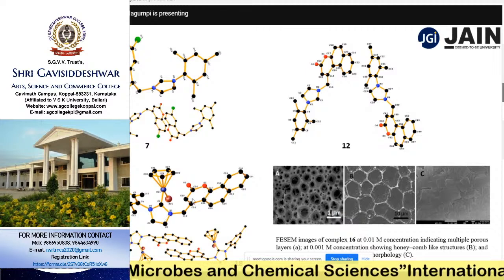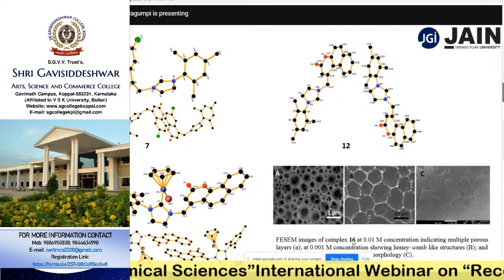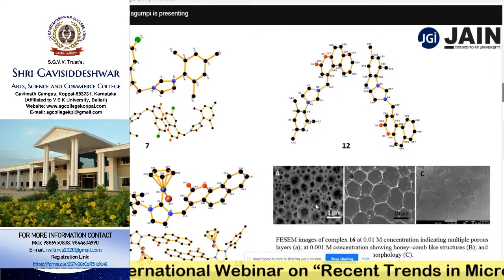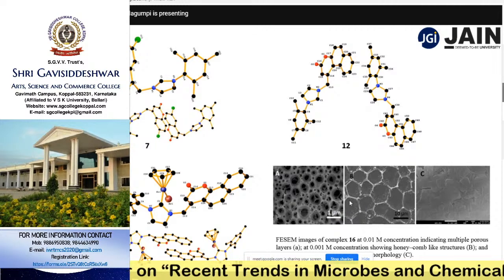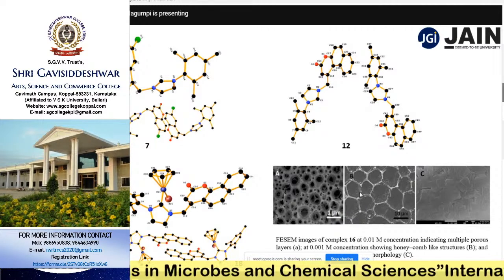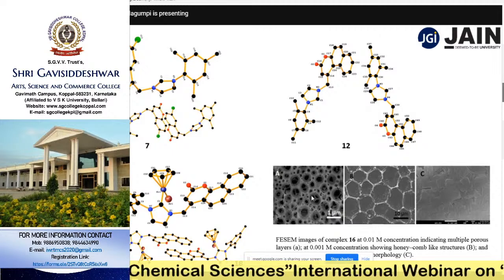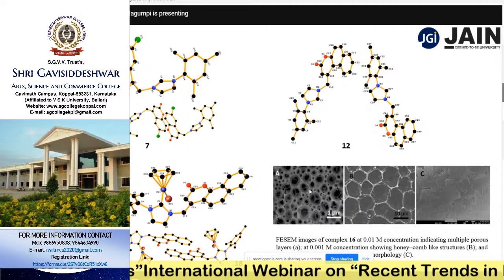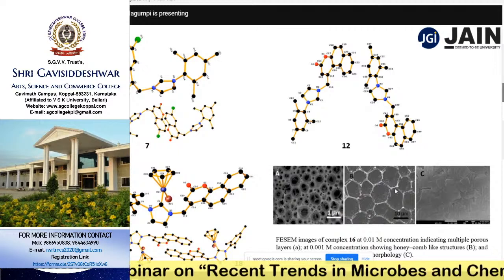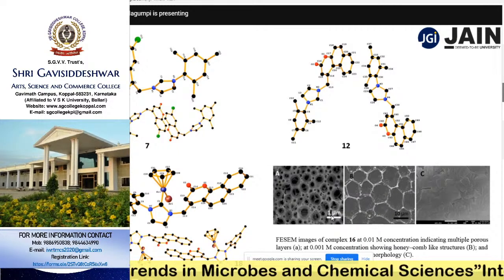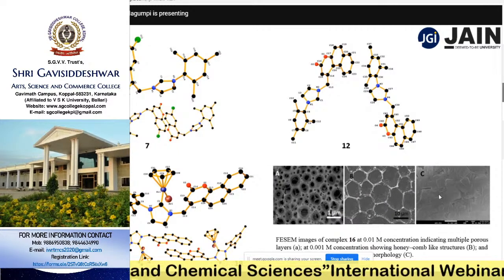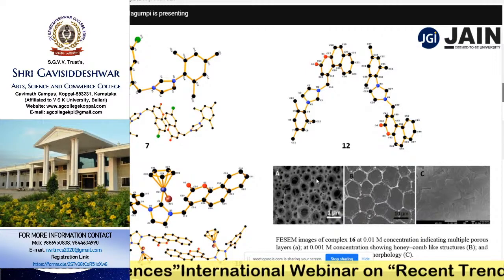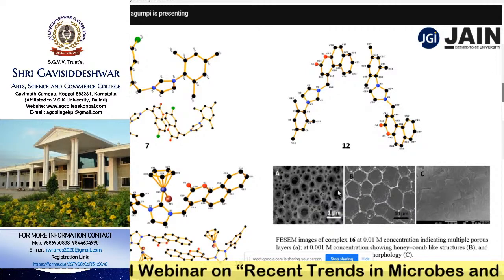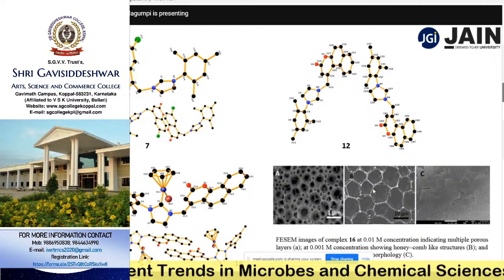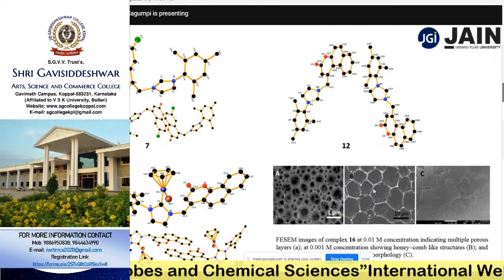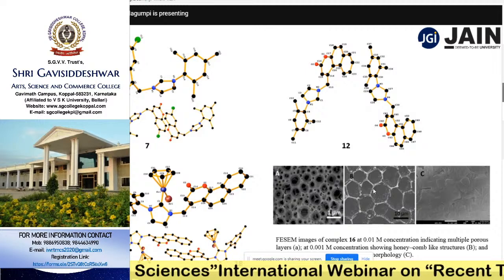Hence, we need to understand the morphology of these complexes. So for that reason, complex number 16 was evaluated for its morphological studies. Interestingly, we could find a highly porous structure with honeycomb-like morphology, in a few micrometers, whereas the other one is an agglomerated structure, which is ignored. So these two compounds have given highly porous honeycomb-like morphology, which helps to interact with the glucose substrate, which is present in the blood samples.